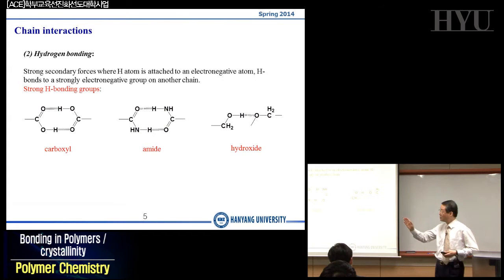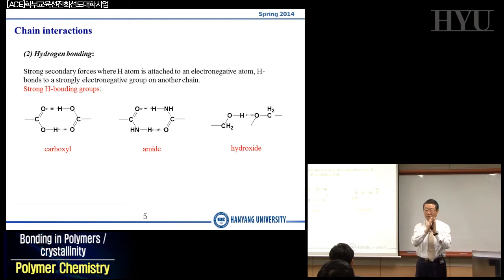But if it's carboxylic acid, it comes downward, so it appears at a lower frequency level, which is around 1680, because of the hydrogen bonding. Right? If you have hydrogen bonding, the IR spectrum is moving toward the lower frequency region.